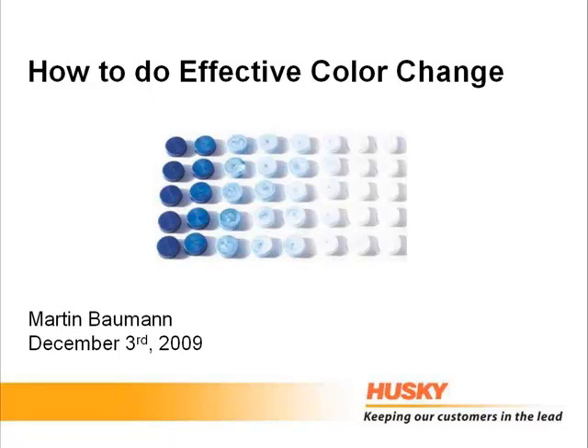You probably could do it for a short period of time, because most resins, even exposed for a short period of time to even higher temperatures, don't become carbon. That's what black specks basically are. That wouldn't happen in a short period. So if you just do it for a quick color change, probably not that big of a problem. But generally speaking, if you're already running that high, it may not help that much, because the percent increase, if you're running already 750 degrees Fahrenheit, another 50 degrees probably won't make a big difference in viscosity at that point in time.